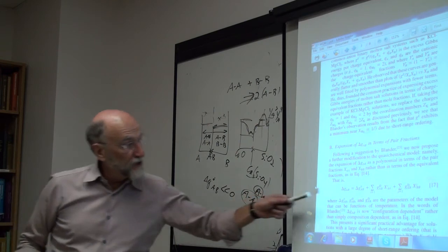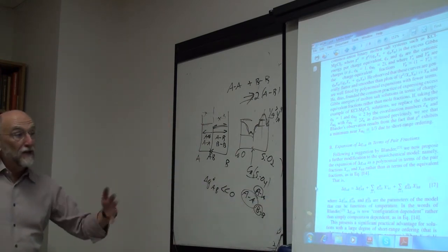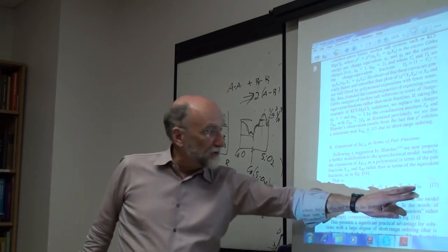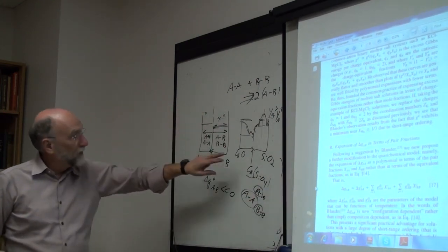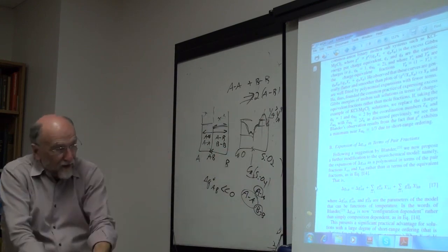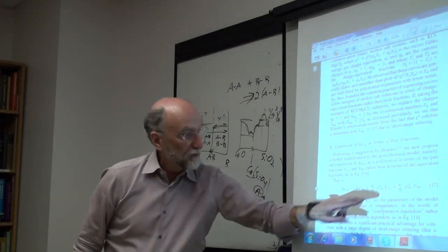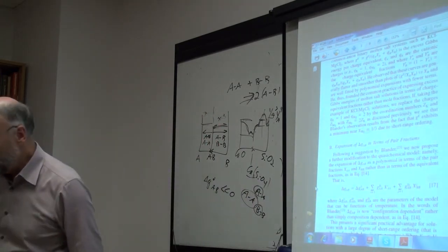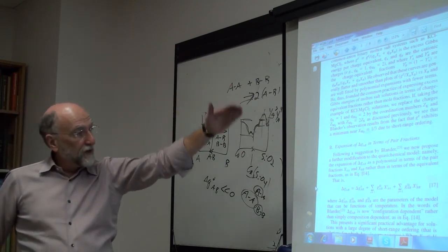Anyway, we find that you can generally get better fits quicker with fewer parameters and much less trouble. You fit this parameter first of all to get you more or less where you want the minimum to be. This is your main term, which will be very negative, and then these terms can be used to fit the two sides independently. Now in FactSage you're not limited to using the polynomial fit or the Gibbs expansion fit.